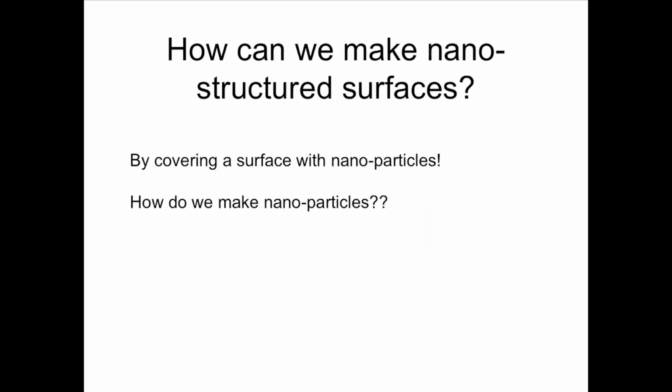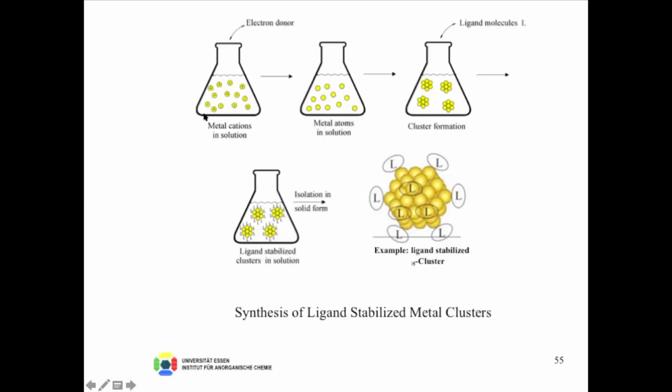So that brings us to the next aspect, which is nanoparticles. The trick to make nanoparticles is the following. You take a solution of metal ions, for instance, gold ions, auric acid, and you put in something that gives off electrons, an electron donor, citrate, but also sodium borohydride is a very good reducing agent, so it gives off electrons easily and you can use it.